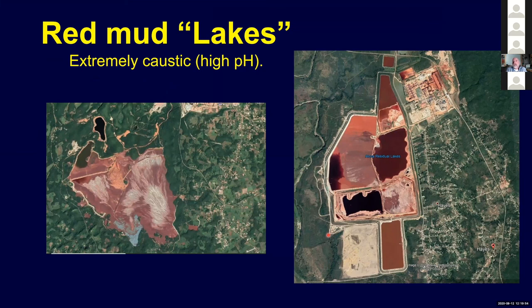They're really quite nasty. They're very high pH, typically around 14, which is the limit of our ability to measure pH, more or less. The red color comes from the iron that's in the system. These are aerial pictures out of Jamaica. And keep in mind that we're producing 1 ton of red mud per ton of aluminum produced, and that's a lot of material. And there's no use for it.